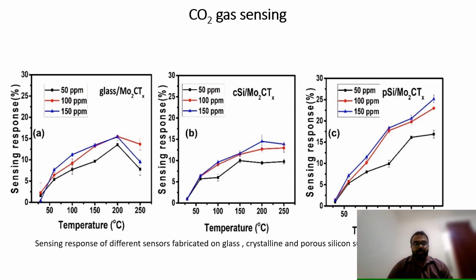Then we compared the performance of the fabricated sensors by depositing MXenes on different substrate materials. First we deposited on a glass substrate, then on a crystalline silicon substrate, and then on a porous silicon substrate. And we used carbon dioxide as the target gas. We observed that the sample prepared on porous silicon exhibited better sensing performance within a range from room temperature to 250 degrees Celsius. Also, we varied the concentration of carbon dioxide.